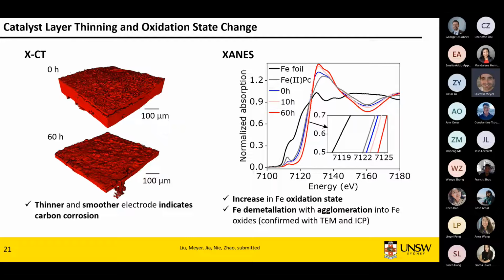So what we can derive from this is basically you have two mechanisms. First one is iron leaching off the surface of the material. At the same time, what happens is you have demetallation, so it forms ions, and then it deposits as iron oxides. And that's actually why you see an increase in oxidation states. It's not from the catalyst, from your active site, it's coming from the products that form on the catalyst surface. So these measurements are good, they're physical measurements. They don't tell you how it's impacting your performance. It just tells you your physical structure is changing.